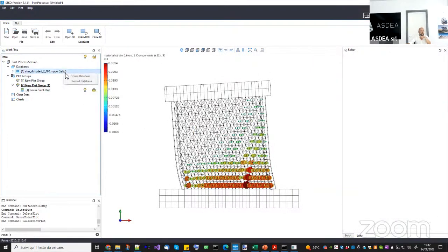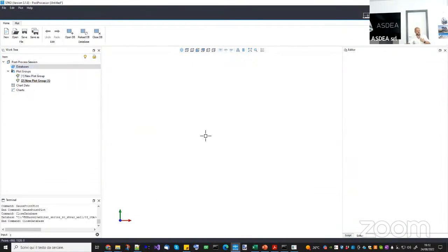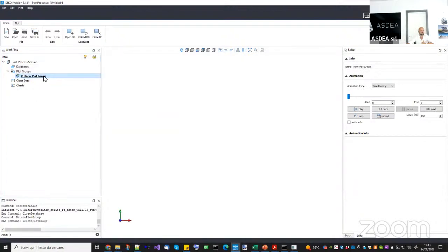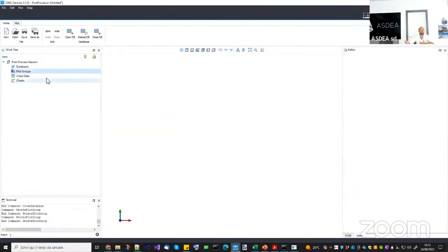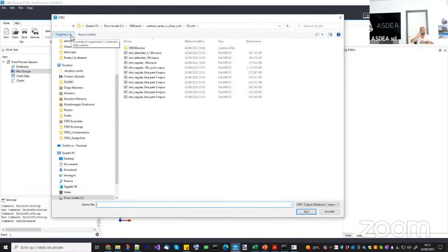Then something else that I tried to do, if you want to play with it, or something actually that I had seen in the continuum models, and I wanted to see if it was a mistake of the continuous models or if it was physical. I did something, and this will actually be the starting point of the discussion of September. One problem that you will always have when you have strain softening is the size effect. The problem is that when you have softening, the size of the microstructure is very important, okay? So in this case, the microstructure can have a typical size, which is the spacing of the rebars, because they determine the spacing between the cracks, okay? So what happens if you do a mesh which is much finer than the spacing of the rebars? I wanted to understand what's going on.